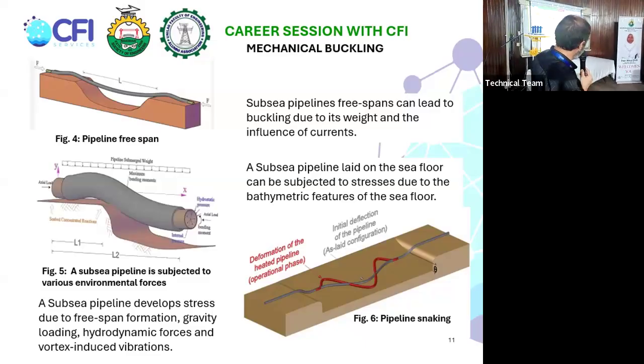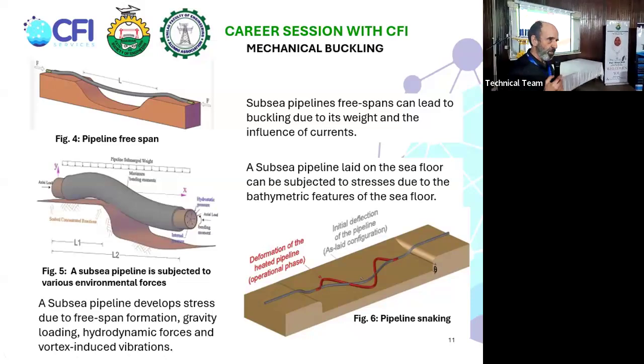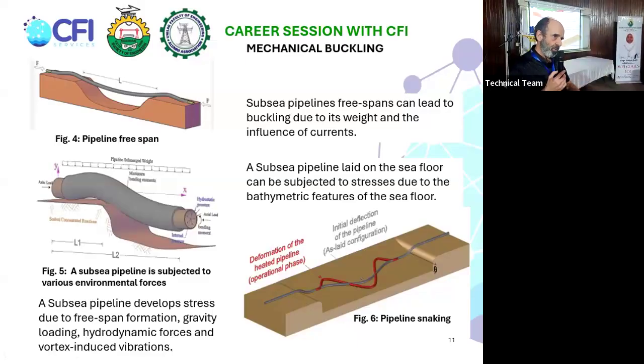And then outside of what we're showing here, there are ways to stabilize it. One of the most common ways is if you buy pipe with a concrete cover, like a 50 millimeter concrete cover around the steel pipe on the outside to add weight to it and to add size to it. So if it starts to slide, it will grab a larger portion of sand that will build a berm as the pipe is sliding, and it will prevent it from sliding very far. Or you can buy these concrete mats. You can buy these concrete blocks tied up as a net sort of, so it's flexible. And you can put this over the pipeline to keep the pipeline secure to the seafloor. That will prevent buckling or sideways moving, and it will also prevent, if the pipe is light, the tendency to uplift and try to float. That will be another way.